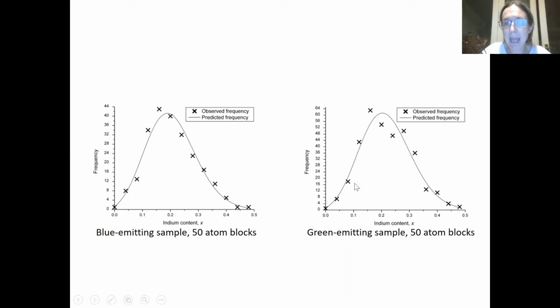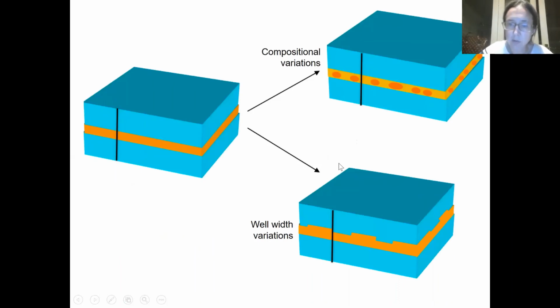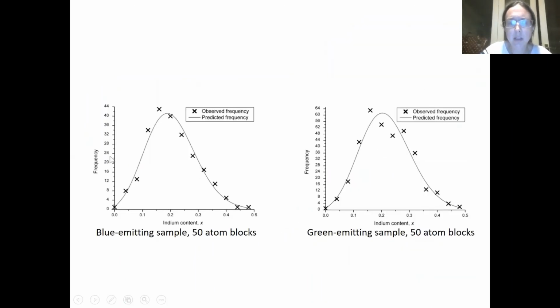And we can compare what we really get, the actual distribution, with these binomial distributions. Here for a sample that emits in the blue, a bit less indium, about 17% or so. Here for a sample which emits in the green, a bit more indium, a bit over 20%. What we can see is actually the data is quite similar to what we'd expect for our binomial distribution, our random distribution.